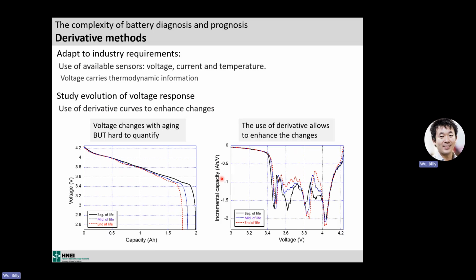So what we decided to do is look at the derivative. When we have a derivative, we enhance those changes. That's exactly the same data here and here. And you can see that on the derivative, we have, so that's a negative curve, I'm going to call that a peak. But you can see that we have some really well-marked peaks. And when the cell aged, that peak disappeared, that peak increased, that peak disappeared, that peak moved. So that's information. Your cell degraded, and the signature of that degradation were those changes.